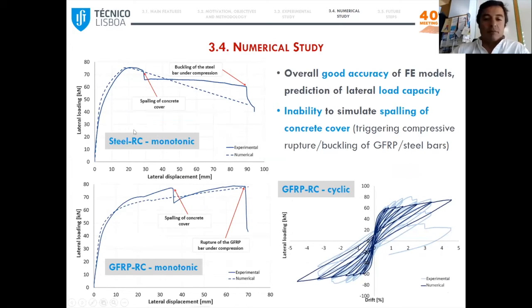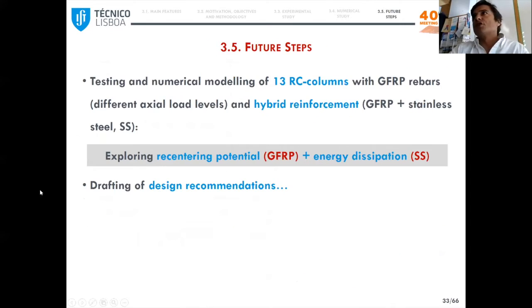So the comparison between experimental and numerical results for the three different tests. So for the monotonic response, I would say the predictions are relatively accurate. So we were able to capture well the lateral load capacity, but of course the models were not able to simulate the spalling of the concrete cover, which then triggered the buckling of steel bars and the failure of the GFRP bars in compression.